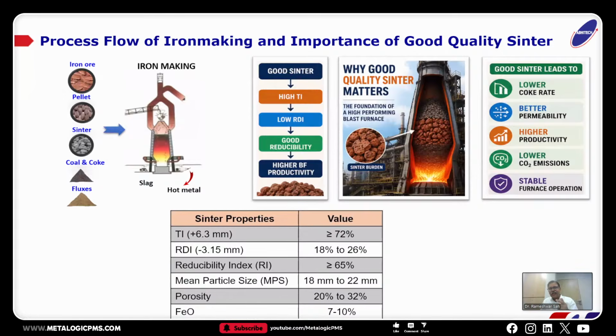And this strong, good quality sinter will lead to very good production and very good hot metal properties. For that, the sinter must have properties in the range we have mentioned. So the good quality sinter must possess a higher tumbler index, RDI properties and reducibility. What are the operating parameters that the sinter makers need, what could be the FeO content, what could be the fuel rate, what kind of porosity could be there, so that it makes the right kind of product.